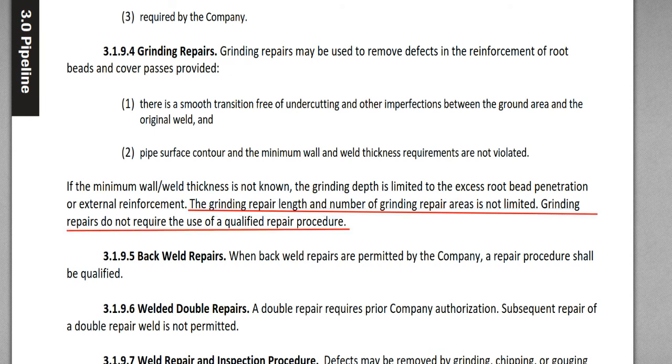The grinding repair length and number of grinding repair areas is not limited. Grinding repairs do not require the use of a qualified repair procedure. Grinding repair doesn't need a qualified repair procedure.